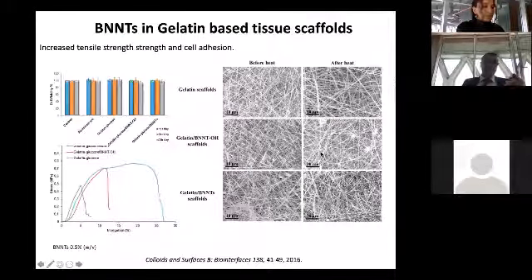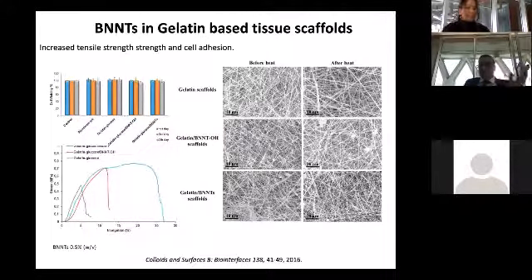The other application is that you use these materials because they have a very high tensile strength, and we added just a little bit, 0.5% volume to mass, into, for example, gelatin scaffolds. Gelatin scaffolds are very good scaffolds, but they have a terrible tensile strength. So they just collapse, and cells cannot adhere themselves and they become useless. When we added this material, it was fantastic. The cells were adhering very nicely and they survived longer.